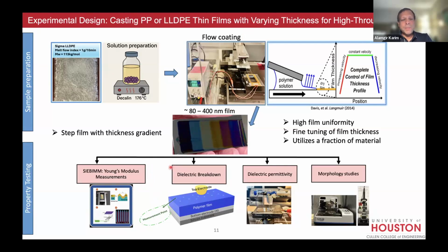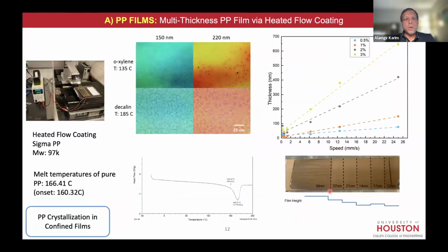All right, we developed a method when I was also at NIST in my early days, where you stretch an elastomer, put this film on it, and if you compress it, it will buckle, and the wrinkling wavelength gives you the Young's bending modulus. Very simply, all you need is an AFM or microscopy, and you can get it. We measure dielectric breakdown as shown here, dielectric permittivity, this is the dielectric constant, and we look at the morphology with optical and AFM. All right, so let's start with polypropylene.